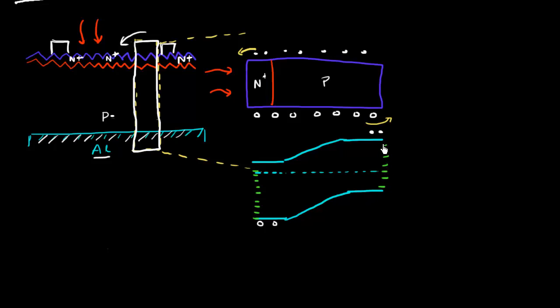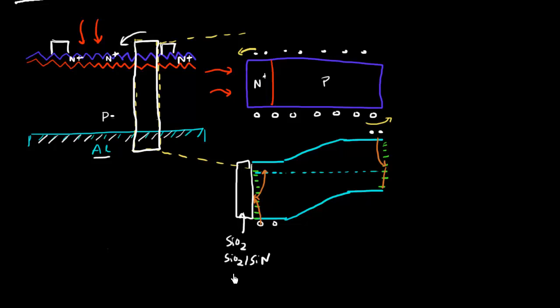If this minority carrier — this electron — reaches the surface, it can essentially recombine using the trap state present on the surface, and it can annihilate the electron-hole pair. Similarly, the hole which reaches the surface can also get recombined. Usually on the front side, at least on the emitter side, people put a very good passivation using silicon oxide or a combination of silicon oxide and silicon nitride, which also serves as a good anti-reflection coating. But this is especially a big problem at the back contact.